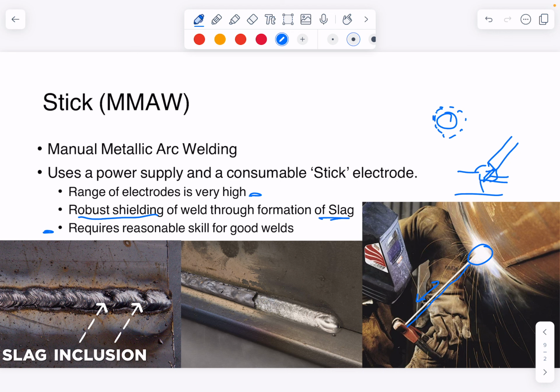If you're going in and out, you get all sorts of changes in the penetration depth, and to some extent you get this sort of stuff. You can see that the weld is inconsistent. We've got inclusions, so just bits of rubbish stuck in the weld. So yeah, it's not a real pretty weld, that one. And that's probably because of the operator not doing things quite right.